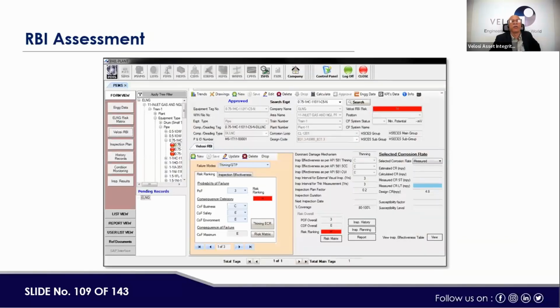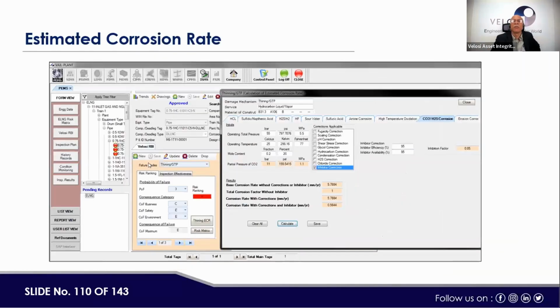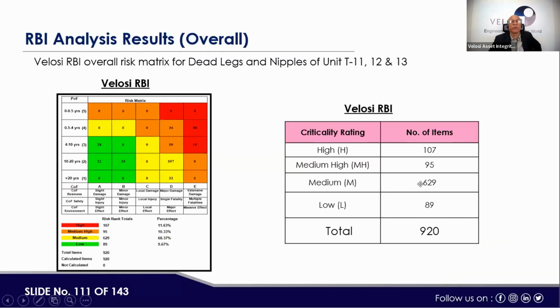So here we have done the RBI assessment by assigning POF, COF for each equipment based on the inspection effectiveness. This is an older screen. Now our new RBI program is more updated and more visible. So here the applicable damage mechanisms are shown, as we can calculate the effect of the damage mechanism and their corrosion rates. Then this is basically the distribution of the equipment as per the risk matrix. If you can see here, like 58, 36, 19, 59, 597, the overall distribution of the equipment.